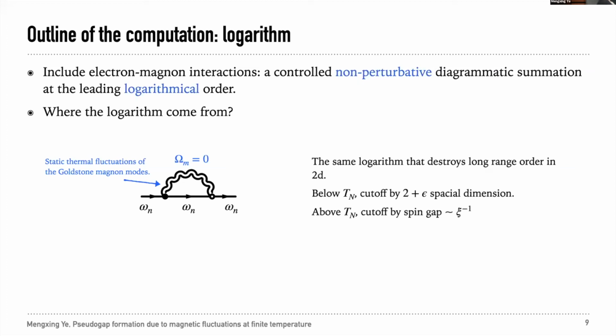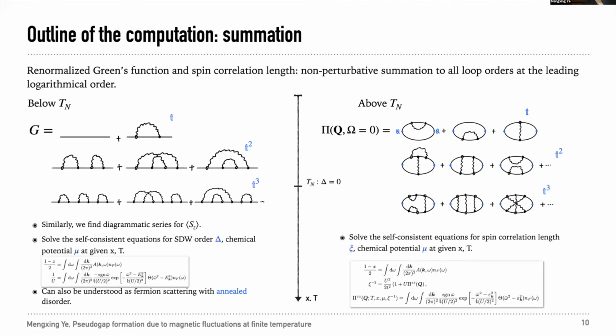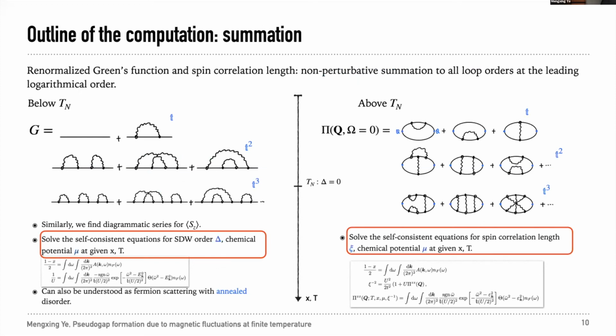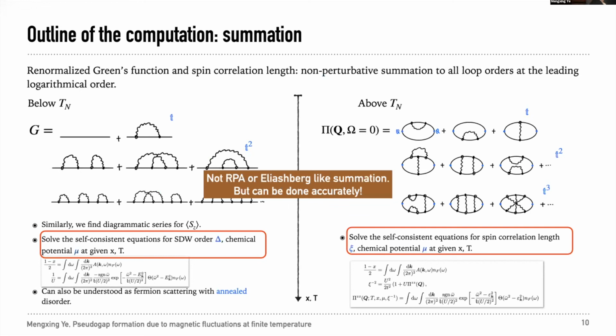Because of the logarithmic divergence, below the Néel temperature, we cut off by introducing 2 plus epsilon dimension. Above the Néel temperature, it can be naturally cut off by the spin gap, which is proportional to the inverse spin correlation length. Next, we can write down the self-consistency equation below the Néel temperature for the SDW order and above the Néel temperature for the spin correlation length. We also keep the chemical potential in our calculation. Schematically, these are the diagrams we need to consider. I will not explain why, but I want to emphasize that this is not any RPA or Eliashberg-like summation, but it can be done accurately here because we only consider the static fluctuations.